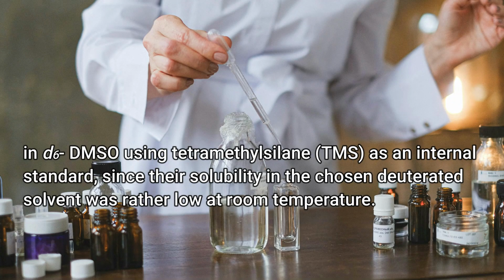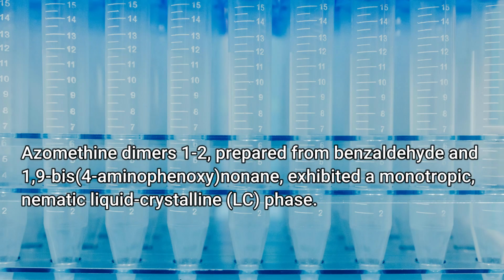In D6-DMSO using tetramethylsilane (TMS) as an internal standard, since their solubility in the chosen deuterated solvent was rather low at room temperature. Azomethine dimers 1 and 2, prepared from benzaldehyde and 1,9-bis(4-aminophenoxy)nonane, exhibited a monotropic nematic liquid crystalline (LC) phase.